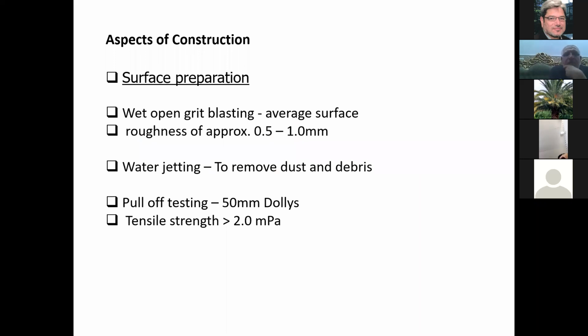Very important here is surface preparation. If your surface is not clean, if it has got debris on it, or if it has got laitance, which is a very weak layer on the surface of the concrete, the technology is not going to work. So what you really need here is to do surface preparation. What we do is we use either water jetting or sandblasting, and this is to give us surface roughness between 0.5 to 1 millimeter.